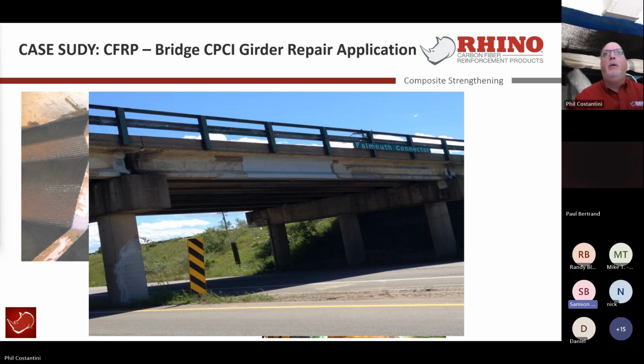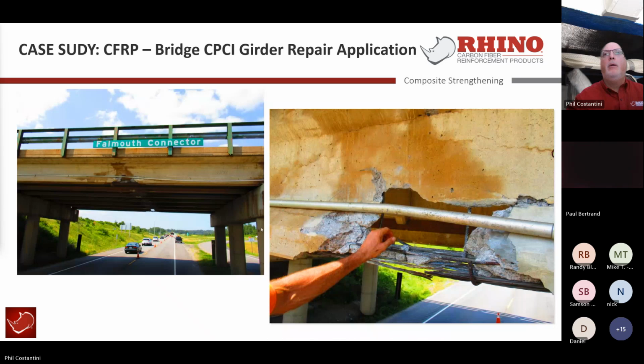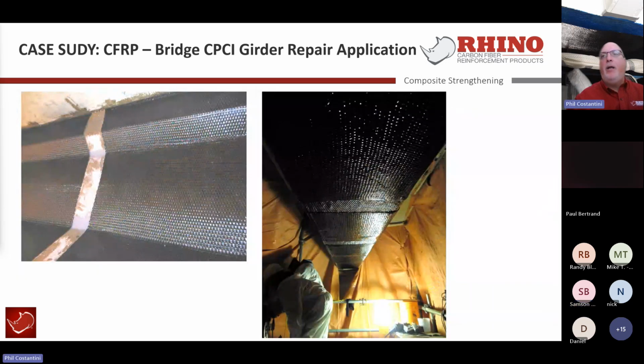Bill, on that bridge there, you don't have to wait for that concrete to cure 28 days. Rather, you measure the moisture that it's less than 5% and you're good. Jackpot, yes. Okay, and that goes with a grout repair too. So if you're going in, the first thing you're going to do is to reinstitute the beam, take off the laitance of it, at the cracks and that kind of thing. And then you've got to wait till you're at the 5%. Then you can go and do the FRP.